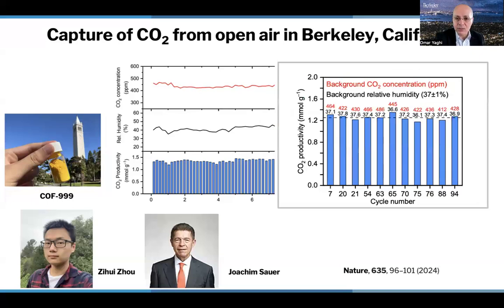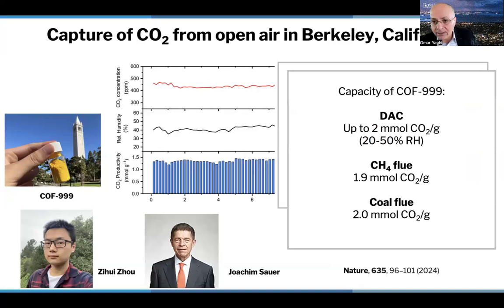This plot shows you how at approximately the same humidity level, you see the maintenance of CO2 capture level. And that's the sort of stability that you need to be able to cycle for many, many years without having to replenish the material. These are the different parameters that we look at. For DAC, the capacity is 2 millimoles of CO2 per gram, way above the minimum requirements for commercialization. It also could be applied for point sources, as you see here, with significant uptake of CO2 per gram of material. So how does this look like at scale?